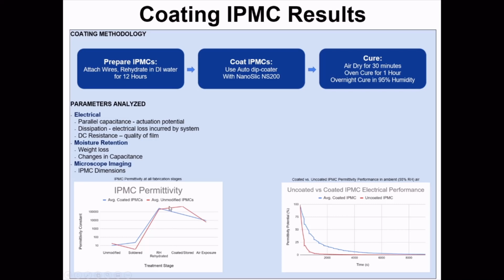the coating is working for these blue IPMCs. So these red ones, the unmodified ones with no coating, are absorbing all this moisture from the humidity chamber they're stored in. RH is relative humidity, rehydrated. And we know this for sure because we actually went over here and we saw it. We pulled them out of water and we said, okay, how are these things going to work? And you can see the blue ones, the coated ones, worked much better than the red ones, the uncoated ones, which means this coating does work. It's hydrophobic. It's stopping the moisture from leaving.